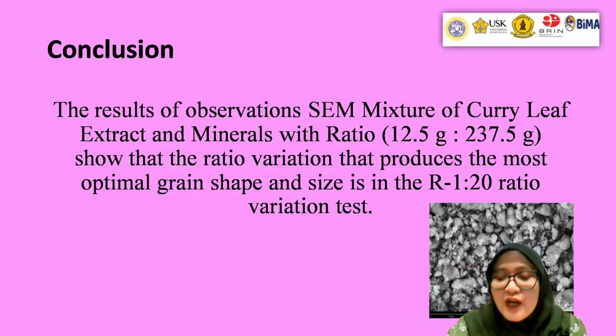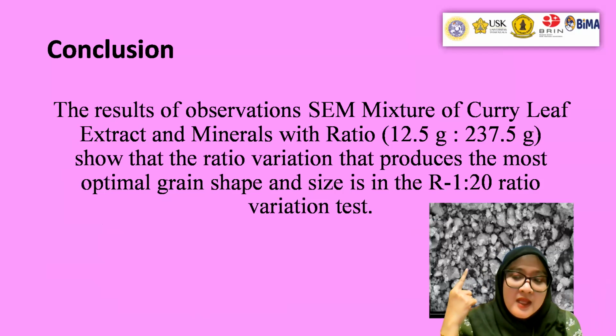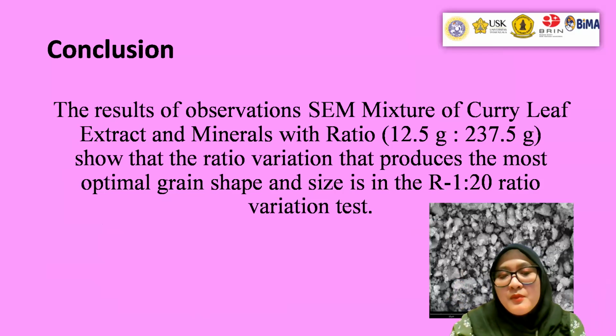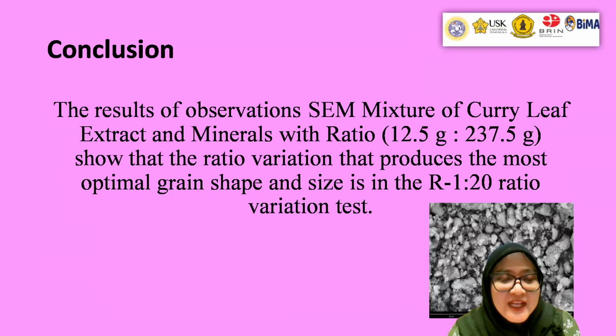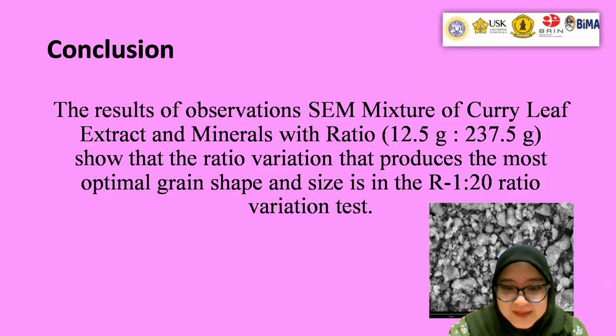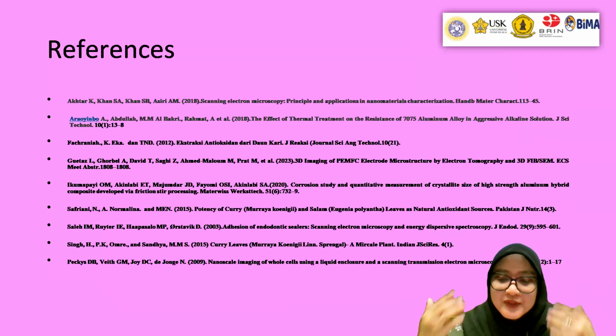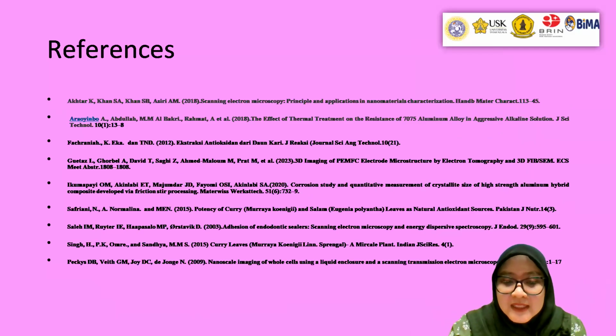And the conclusion of this research, you can see in the figure that the result of observation of the mixture of curry leaf extract and minerals with ratio 12.5 gram between 237.5 grams showed that the ratio variation that produced the most optimal grain shape and size is in the 1:20 ratio variation test. And these are the references of this article.